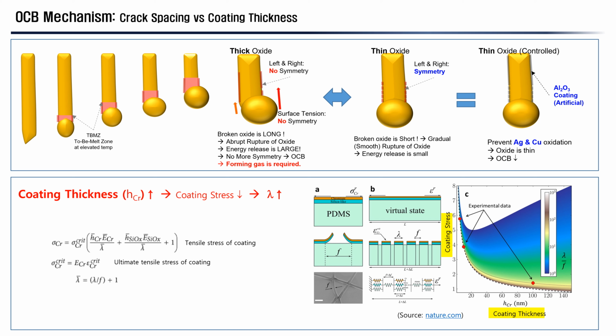On this slide, I'm going to give you a little bit of a sense of what the OCB mechanism is like. I'm going to explain why OCB is affected by the oxide on the wire surface and oxide thickness. When electrical energy is supplied to the bond wire, the bond wire is going to melt and a molten ball is going to grow. But the bond wire right next to the molten ball, I would call it the TBMZ, the to-be-melted zone, is nothing but a solid. Elevated temperature is very hot. When a metal is exposed to high temperature, it is going to experience metal oxidation.